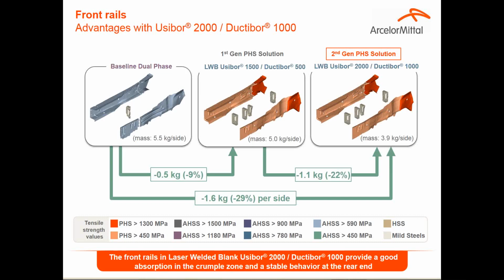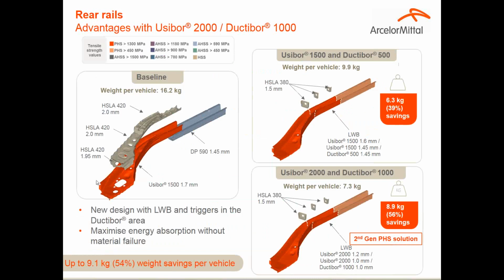And looking at other solutions, as for example the rear rail, we can see similar benefits by considering the same concepts. In this case, on the baseline, we see three parts. One hot stamped, one cold stamped on the bottom to absorb energy, and one patch added for, again, both reasons, stiffness and crash. And what could be the laser welded blank solutions?